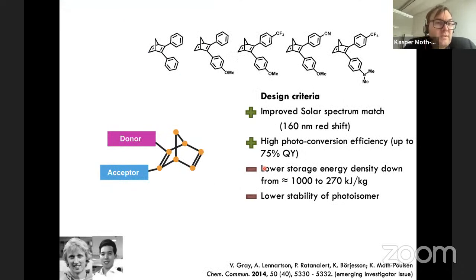So in our first series of molecules, we made donors and acceptors like this with phenyl groups, and then we had the donor methoxy group or an acceptor with cyano group, for example, and a stronger donor here. And this series of compounds had a much improved solar spectrum match. They could go into the visible light. They had a much higher photoconversion quantum yield, meaning that the chance of the photoisomerization event was up to 75%. But also the molecular weight was much higher than the unsubstituted one, so we lost in the energy storage density, and the stability of the photoisomer went down from years to a few hours. So there was something we had to work with to improve this further.